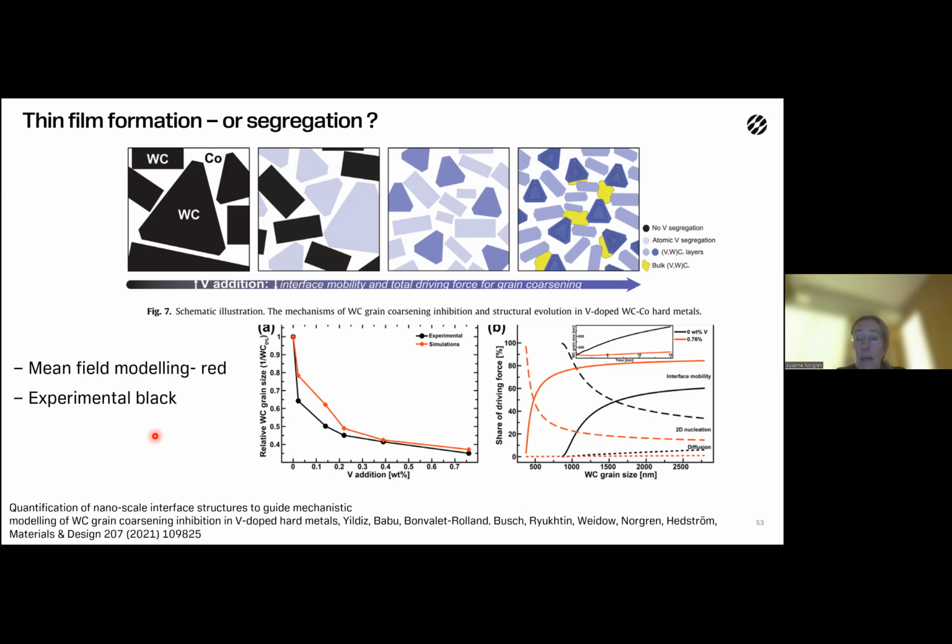And this is very interesting, that it seems as if, depending on where you are, so this is a little bit in agreement with the Japanese article, depending on where you are in the carbon activity, a larger part of the driving force is consumed by growing the interface compared to the nucleation. I would say that this is something that we are still working on and trying to understand a little bit more in detail.